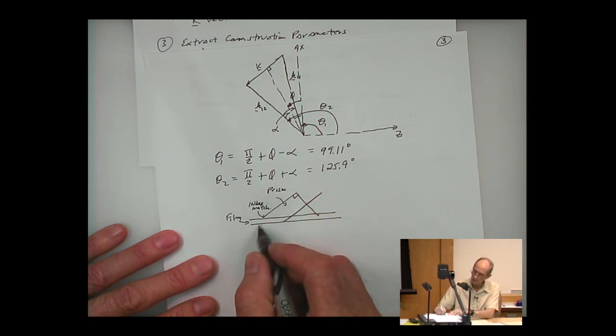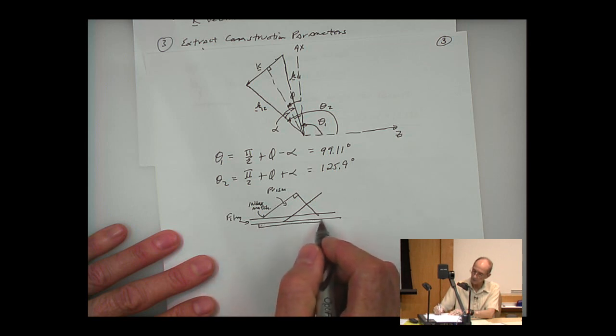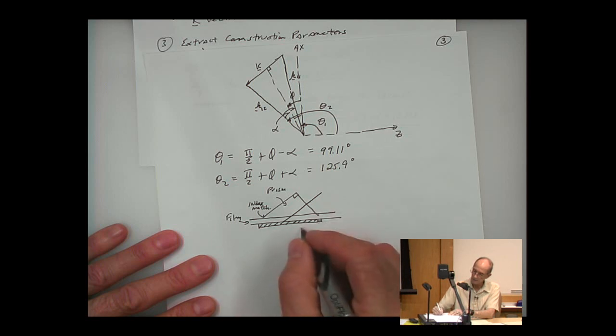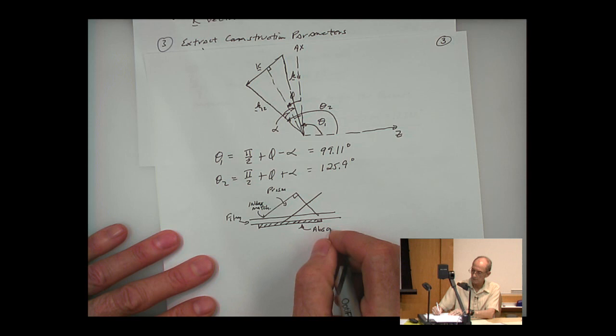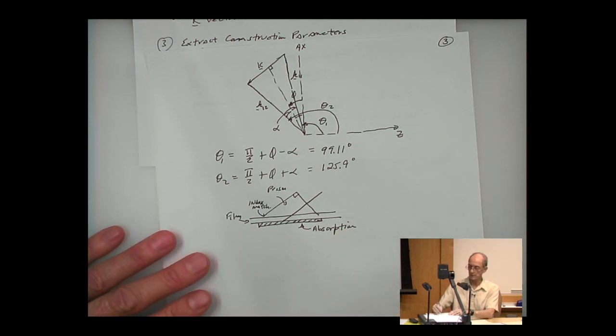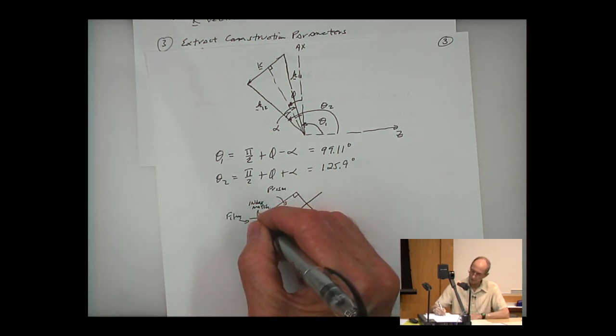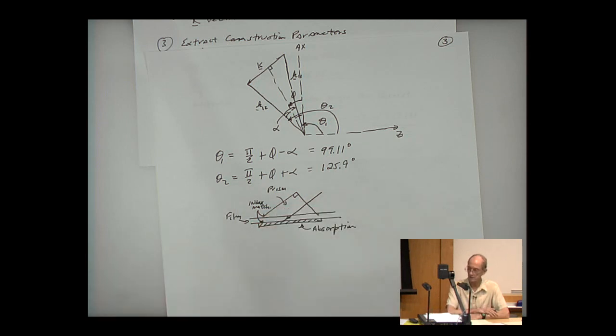And then normally when you do a recording like this too, so this brings up a good point, we'll have to do some absorption here. Usually we use a very dull black paint on the backside of a cover glass and index match that as well to the glass, so you don't get surface reflections there. So that brings up a good point.